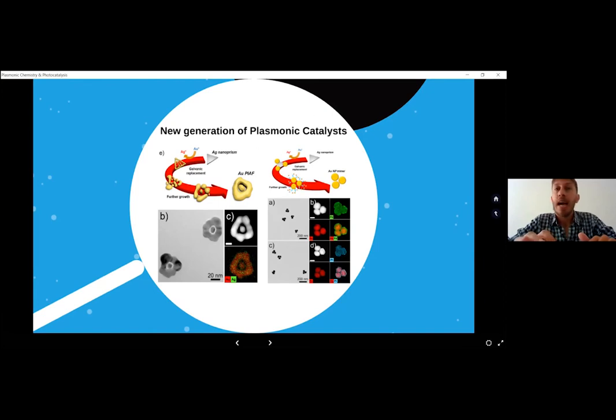Another type of nanoparticle that we also designed specifically thinking about plasmonic catalysis has these kinds of trimer structures, where we have three hotspots in a single structure. And we coated these gold nanostructured trimers with a thin shell of platinum and palladium, which are also really good catalytic materials. And we prove here the effect of having hotspots in the structures, right? As we know, and as I showed in the previous example for the single particle measurements, hotspots are a key principle in order to build efficient plasmonic catalysts, because the field can be highly enhanced inside and outside the nanoparticle, right? So the absorption and the confinement of light is huge when you have hotspots present.